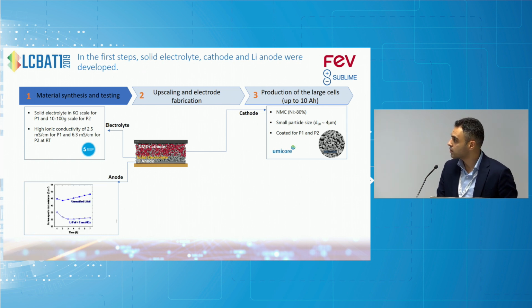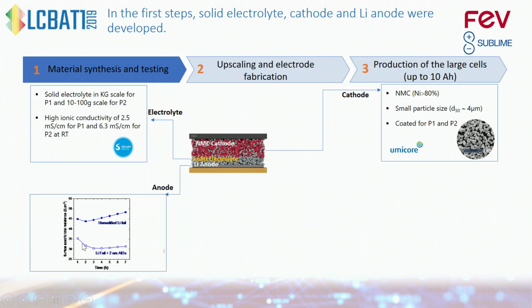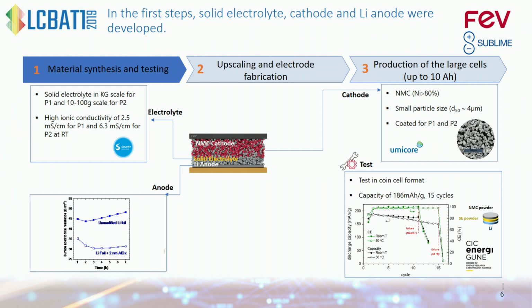And a very recent result we achieved was to get a stable coating versus sulfide electrolyte with a very low interfacial resistance, as you can see. This was achieved by ALD coating of aluminum oxide on lithium anode. Then we put these materials to the test. We fabricated coin cells with this type of material that was developed, and you can see we can get high capacities at room temperature. So it shows the proof of concept.